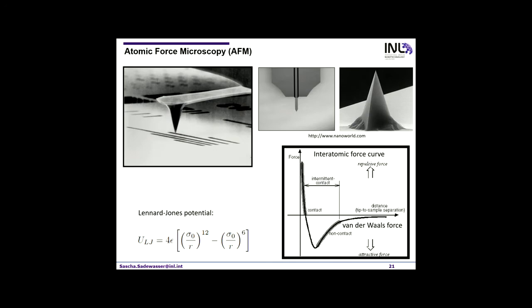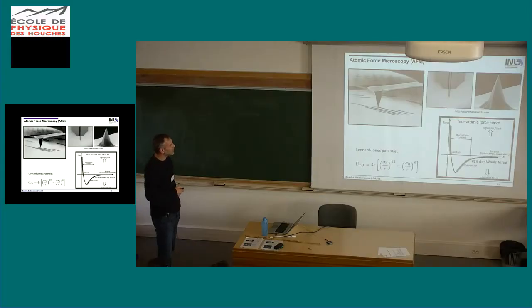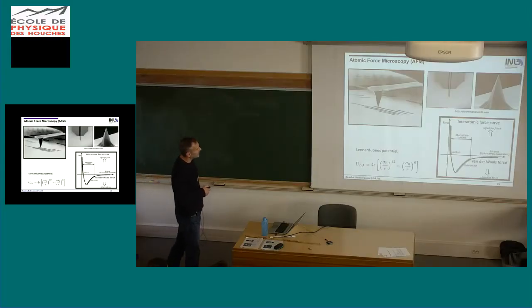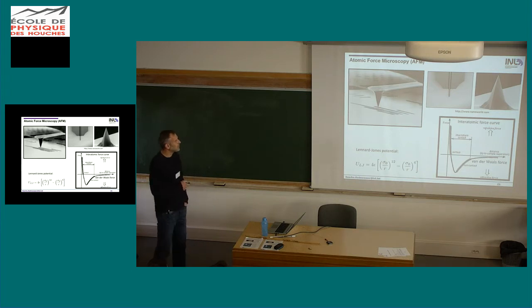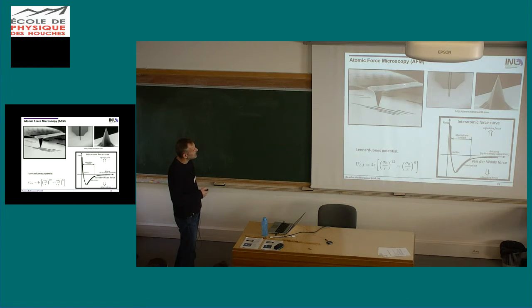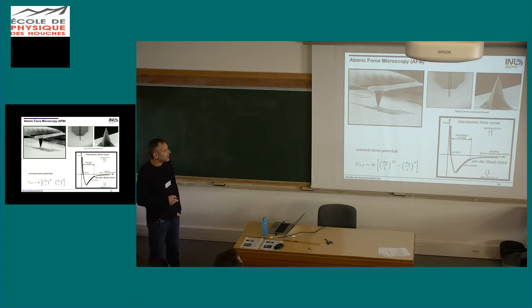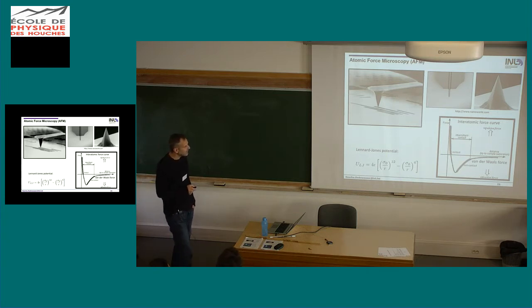Okay, so nowadays things look a lot more professional. We have now 25 years or more of AFM, no, 35 years. So nowadays you use actually silicon cantilevers with a very well-formed, nicely shaped tip. This is all done by micromachining in clean rooms. So these tips are very sharp. They have a tip radius of 20 nanometers or even less sometimes.